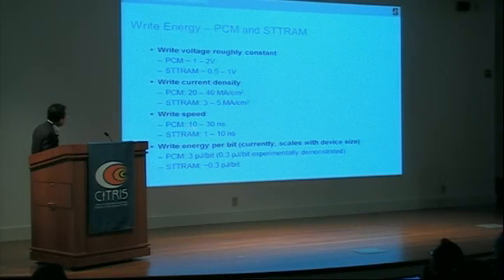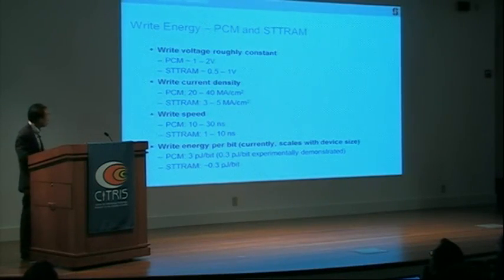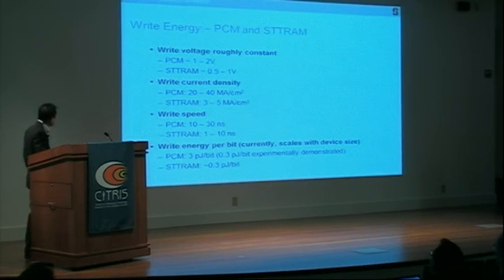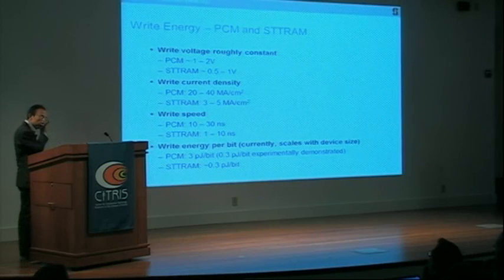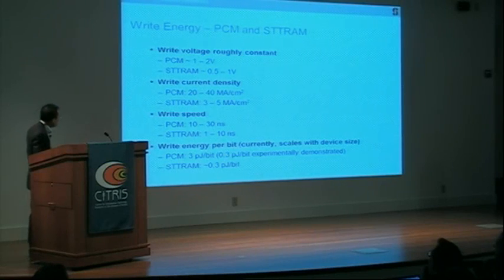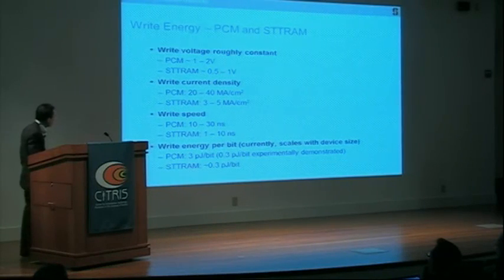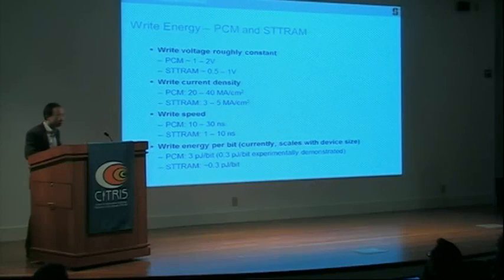The write speed for phase change tends to be of the order of 10 to 30 nanoseconds or so. You can have faster or slower ones. And STT-RAM is about 1 to 10 nanoseconds or so. So for the write energy per bit, for the devices that we're making currently, it obviously scales with the device size. For phase change, it's about 3 picojoules, and for STT-RAM, it's about 0.3 picojoules per bit.